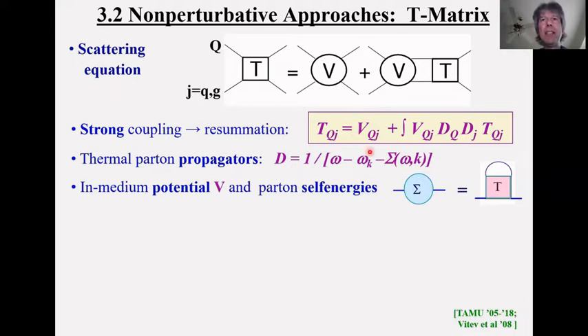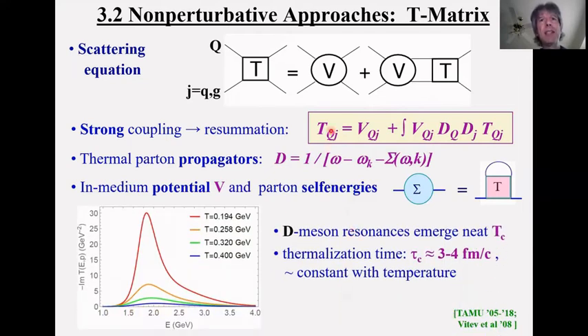The other key ingredient is this potential here. Now, the question is, how can we relate this potential to the information that we possibly have from lattice QCD? And I'll come to that in a moment. First, before going there, let me show you some typical results that you get for the scattering amplitude. If you implement an in-medium potential and carry out the self-consistency procedure, then you find that indeed close to the critical temperature, you have this very large scattering amplitude, leading to, in fact, the formation of D-meson-like resonances.